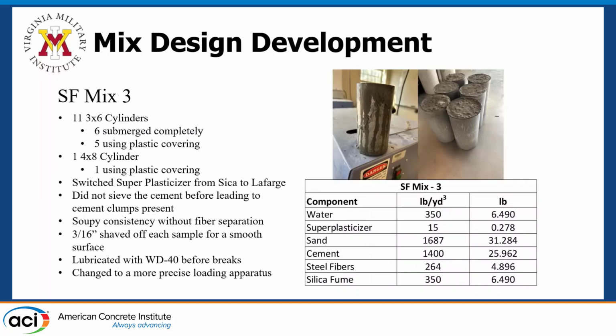So this is mix 3. Great mix, to be honest. However, the thing about our concrete lab is it's in the middle of the mountain region of Southern Virginia. There's a little bit of humidity, so when you go to open up the cement bags, you've got to sieve them properly because you're going to have clumps that are a result of the humidity. And that's what we had. So we ended up finding that cement clumps were present in each sample. As you can see in the samples there, we actually lubricated each sample using WD-40 on both ends, and that led to a complete shear break throughout.